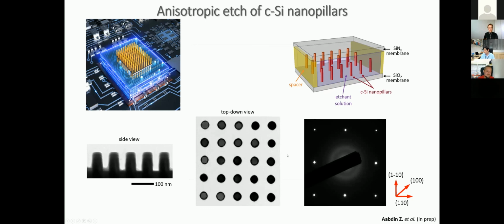And then we look at the etching, right, of this thing, how etch happens. And bear in mind, it's a silicon oxide membrane this time. And when you do KOH etching, unfortunately, KOH reacts with the oxide, and it etches at a much higher rate than a nitride. So you have to be very careful. And we've occasionally broken the membrane inside our TEM, and then I think our lenses are contaminated with this KOH and all these unwanted chemicals. So I wouldn't go and touch our lenses at this point.